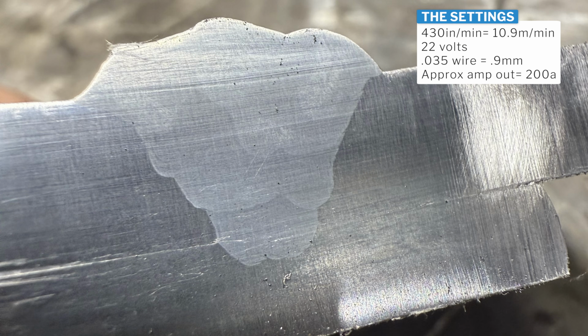So here we have the multi-pass weld, and the first thing that struck me as interesting was that it actually penetrated into the backing strip pretty decently. That's more than I would have expected, so that looks good. What I don't like about this is on the right side of that, there's an absolute straight line, and to me, that's guaranteed lack of fusion there.